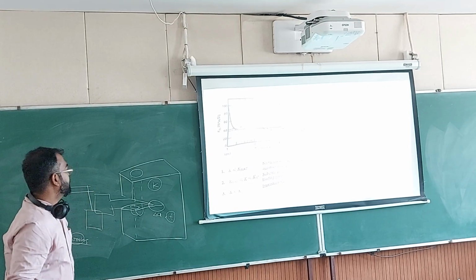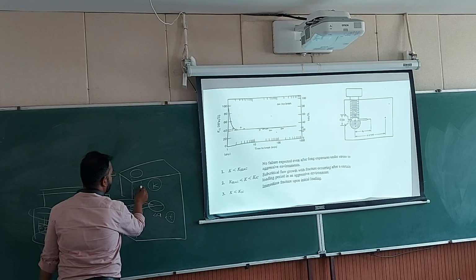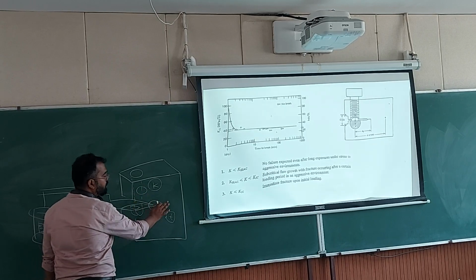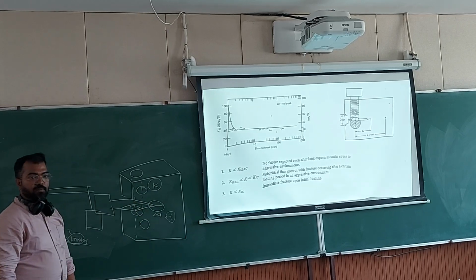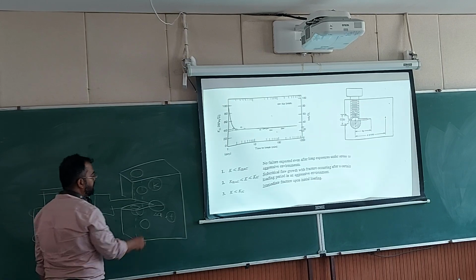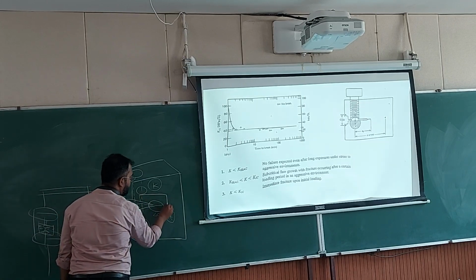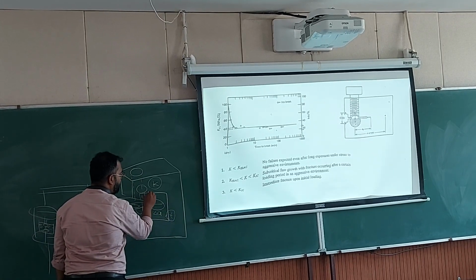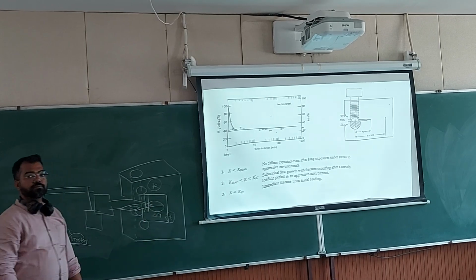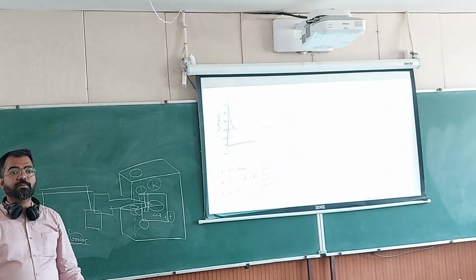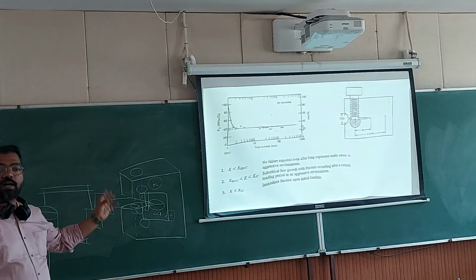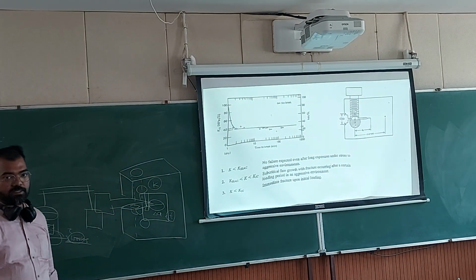So in this case, you take a conventional CT specimen, then you do a fatigue pre-cracking. Once you do a fatigue pre-cracking, then you make a smaller specimen out of that, and then you put a bolt there. You do fatigue pre-cracking on CT specimen, make a half CT specimen for this kind of testing.